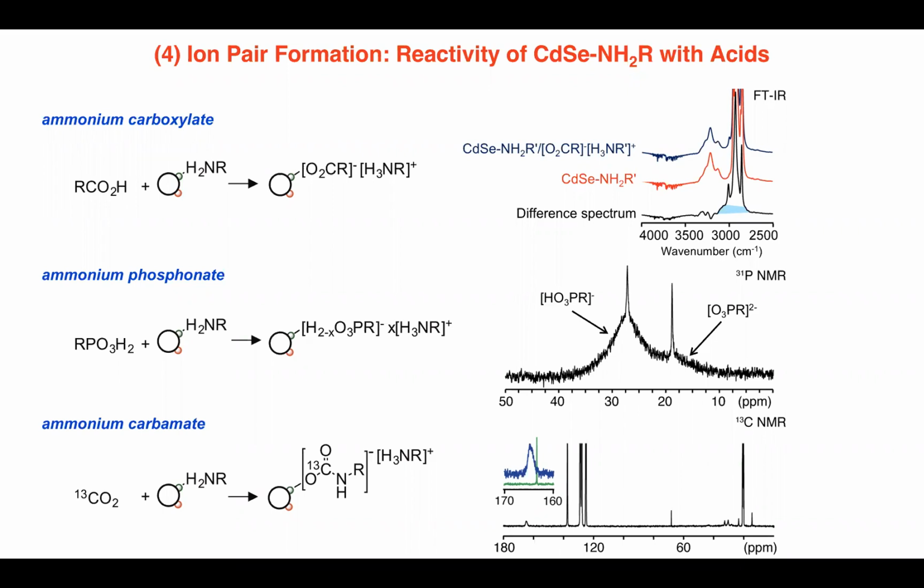How would you do that? The best way that we found was to look at the FTIR spectrum in the region where you see an ammonium vibration. And that ammonium, OH and NH modes are out around 3,000 to 3,500. If there's water in your IR spectrum, you get a big broad band.